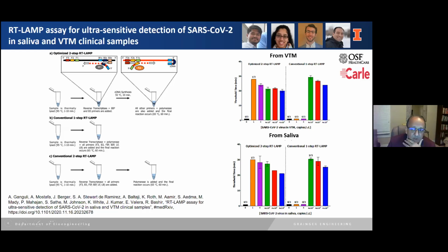The standard one-step RT-LAMP, which is still reasonable, allows us to go to, let's say, 4 times 10 to the 1, 40 viral particles per microliter, which is very sufficient for most clinical applications. But with this improved process, we can go down to just a few molecules. And again, this sensitivity is very similar to the PCR sensitivity.